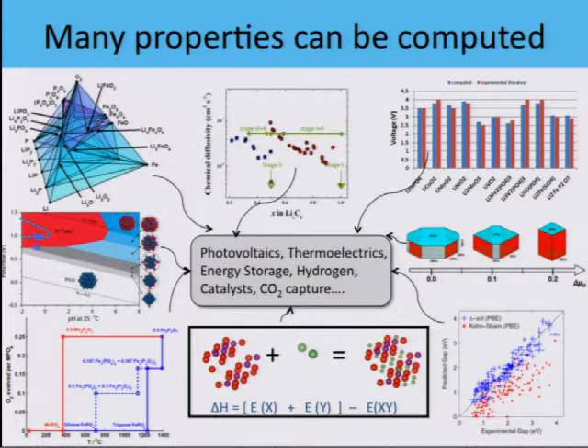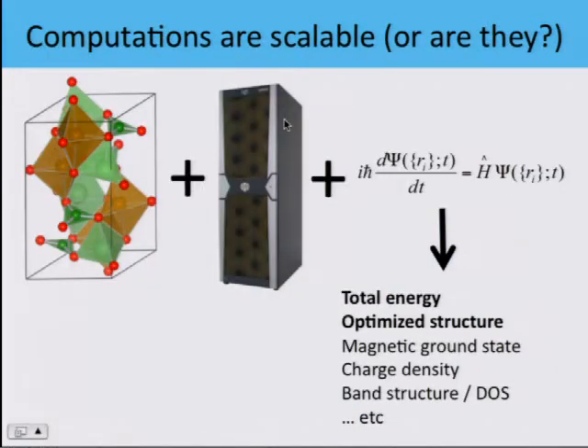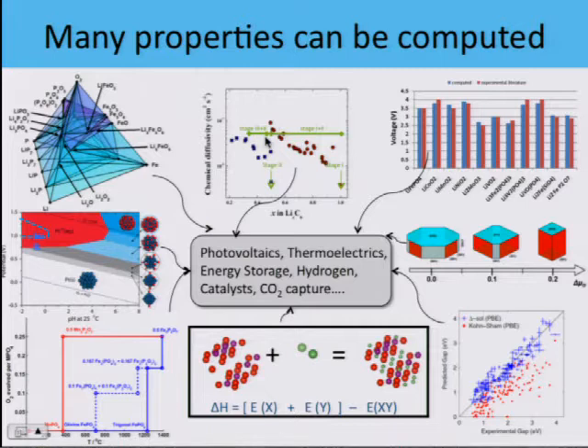There's the diffusivity of lithium. That's the second graph. This one in graphite, that is important for lithium-ion batteries. This is voltages for different cathode materials compared to experiments, and as you can see, we do pretty well. So there are no fitted parameters in here, but we can calculate these voltages really well. Then there was the dissolution of the platinum particle. These are particle morphologies. We can calculate that from surface energies.